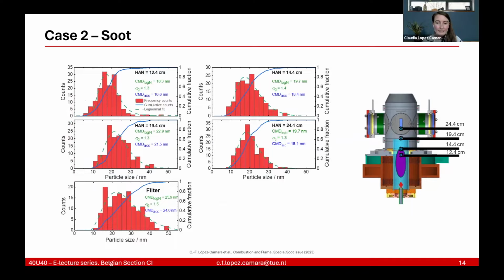For soot, it actually happened the opposite. When you are, for example, at the lowest height above the nozzle, so 12.4, which is the top left plot, you have about 16.6 nanometers. However, as you move farther from the nozzle, let's say the filter, which is the last plot at the bottom, you see that the size is already 24 nanometers, and that's in diameter, because for soot particles the approach that we use is that they resemble spheres, so we basically count the diameters. And what it tells us is that the diameter in general increases as we move farther from the nozzle, which tells us that there is still surface growth when the particles are being moved away from the nozzle.